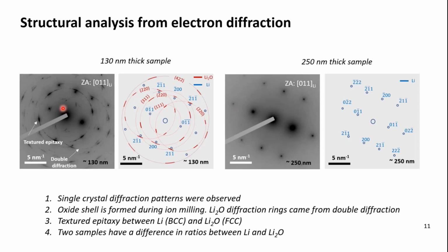And surprisingly, this interface is commonly seen between the BCC and FCC structures generally. And BCC in this case is lithium, and the FCC structure is lithium oxide in our case. And surprisingly, I didn't see such lithium oxide diffraction in the thick sample. Therefore, I hypothesized that there are different ratios between lithium and lithium oxide at the two different thicknesses along the beam axis.